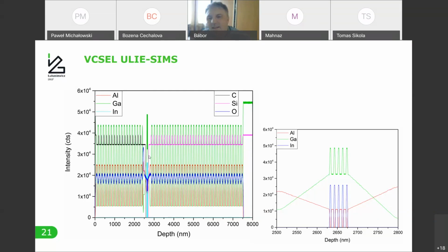So this profile took something like 20 hours to obtain, but it was fully automated. It really took a lot of time to make such a procedure, with all these changes of the primary energy, current, and polarity, even with the inclusion of these polishing service moments, where I was at the same time readjusting the primary beam and also polishing the material itself.